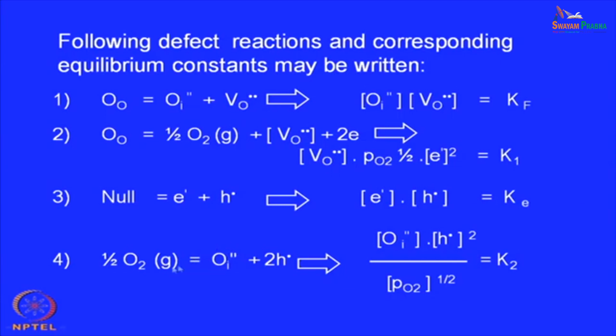Based on that assumption, if more oxygen gas is available outside in the atmosphere, part of it will certainly pressurize the system to go in as oxygen interstitials, and once the oxygen interstitial goes in, then an electron hole will be created.